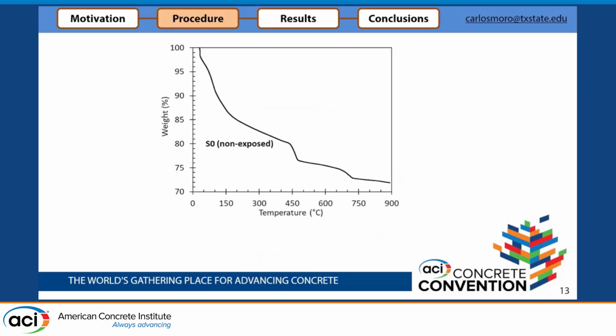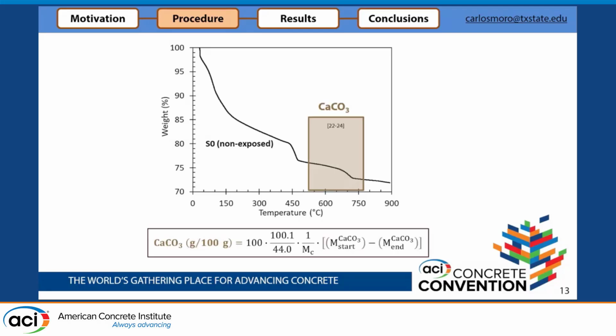Then, in order to explore that further, we did some TGA analysis to quantify the CO2 capture, and XRD analysis. For the TGA, we first analyzed the non-exposed sample, and we can calculate the calcium carbonate content that basically happens in this region right here, after 550 until around 750 more or less. And we also quantify the same calcium carbonate in the exposed sample. So basically we are subtracting the calcium carbonate content of the non-exposed sample from the exposed sample. In that case we can see the CO2 capture that was taken during the CO2 curing.